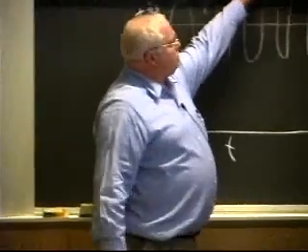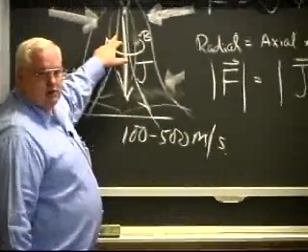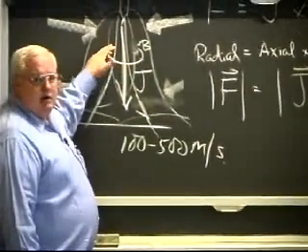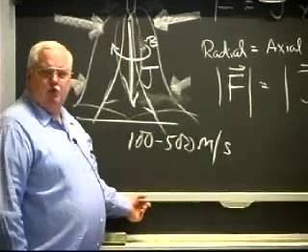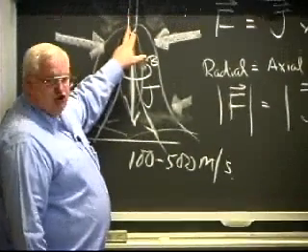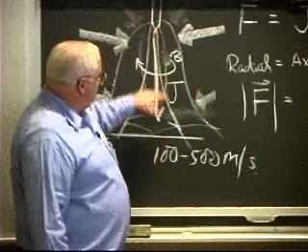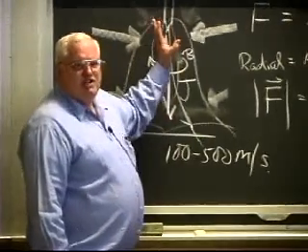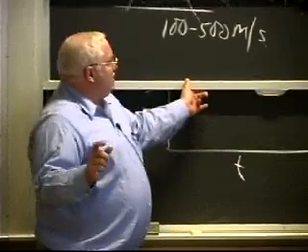Another thing you can do is change, if you're doing flux shielded welding, the composition of your flux. If you have things like barium or lithium, things in columns 1 and 2 of the periodic table, you can get a much sharper cathode spot. Or actually, that's going to be the anode spot, cathode spot. Anyway, you can change the arc characteristics and essentially get stronger plasma jets,